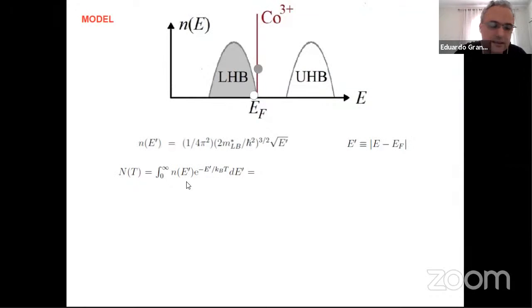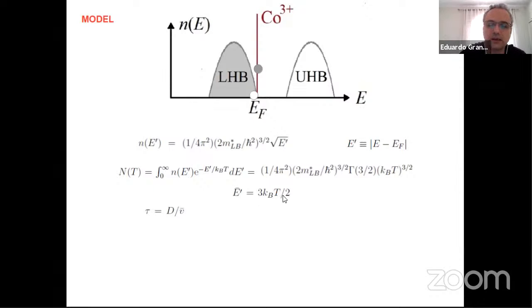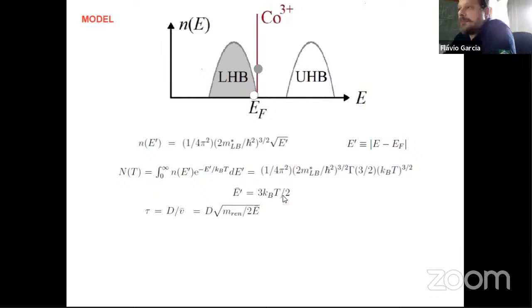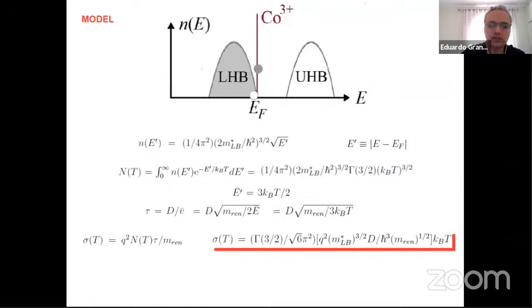And by just statistical physics, you can actually calculate how many holes you have for each temperature. You know pretty much the average energy of each hole, right? Because from statistical physics, you know that it's 3/2 of Boltzmann constant times temperature. And then you evoke a Drude model. Again, for those who studied solid state physics in the graduate course, you saw the Drude model. And then from the number of holes, you may estimate the conductivity. And just by doing the math here, you predict that the conductivity as a function of temperature should be linearly proportional to temperature. So that's exactly what we saw in our experiment. So that explains pretty much.